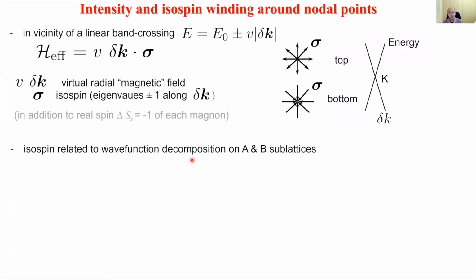Now, one way to think about this intensity winding around the nodal points is in terms of the concept of isospin. So in the vicinity of linear band touching, the dispersion is linear like this. So it can be written in the form of a Zeeman term, where we have a radial magnetic field, V delta K. This is virtual, of course. And sigma stands for an isospin, which can have eigenvalues of ±1 along delta K. So this isospin is radially out for the top band, such that the energy is plus V delta K. And for the bottom band is radially in, such that the energy is minus V delta K. So that explains this linear dispersion.